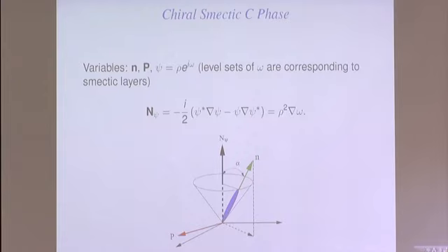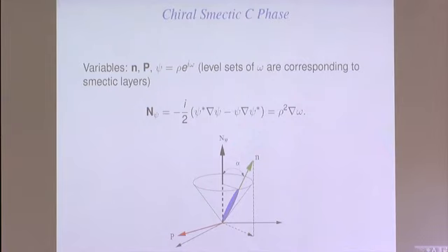Okay, and when you write psi as the translational order parameter for smectic, you can rewrite it using a complex field, and then you define n psi in this form, which is exactly rho squared gradient omega. In that case, rho equals 0 is nematic, rho constant is smectic, but in general rho is not constant in the smectic case.